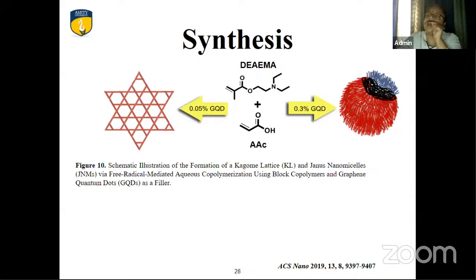So interestingly, with a higher percentage, say 0.3%, this is the Kagome, which I said, and this we have given as the planar tiling of the Star of David, and this one is the Janus. So at higher percentage, GQD allows selective tuning of the interfacial property of the copolymer, breaking symmetry due to surface incongruity, producing exotic Janus nanomicelles. Herein, with the help of a suite of characterization, we delineate the mechanism behind the formation of Kagome and Janus, which forms a depot of heightened drug accretion with targeted delivery of 5-fluorouracil in colon cancer, which is validated by gamma scintigraphy.